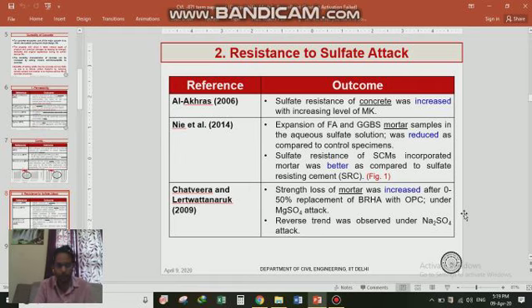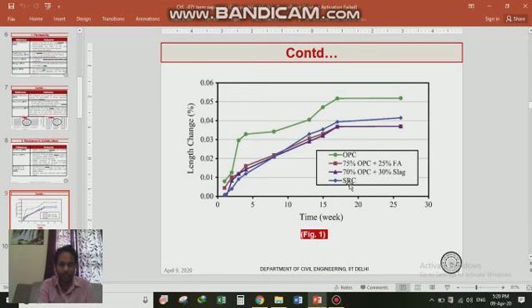In 2014, Nie et al. studied the expansion of fly ash and GGBS incorporated mortar samples in aqueous sulfate solution, and they concluded that resistance to sulfate attack was improved as compared to control specimens. Even it was higher than that of sulfate resisting cement, as we can see in the figure. Here the expansion, that is length change percentage, is for OPC, this is for SRC, and this is for fly ash and slag. So we can conclude that the length change is quite less than that of SRC when we incorporate the fly ash and slag.